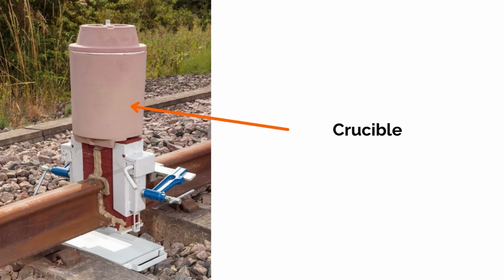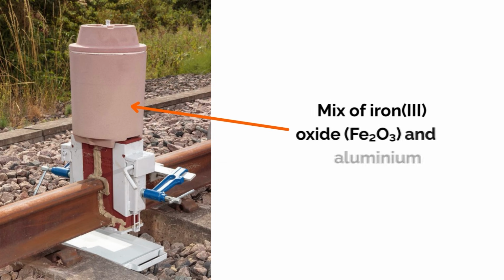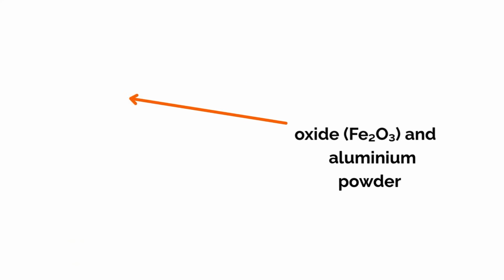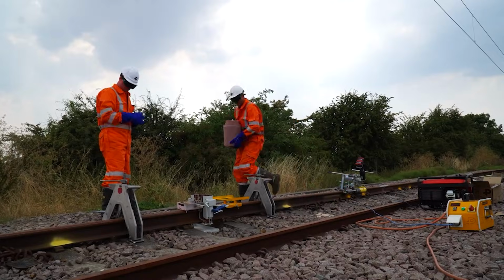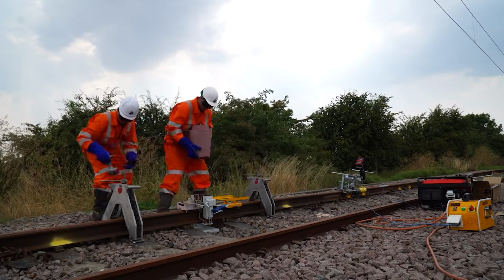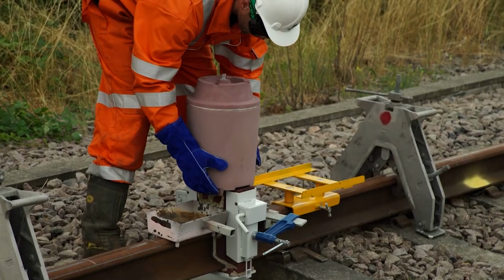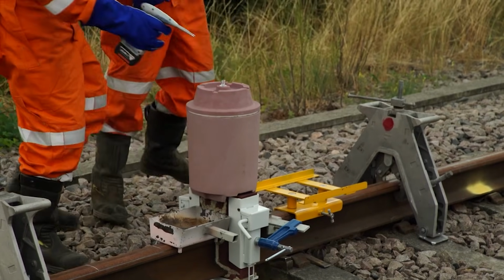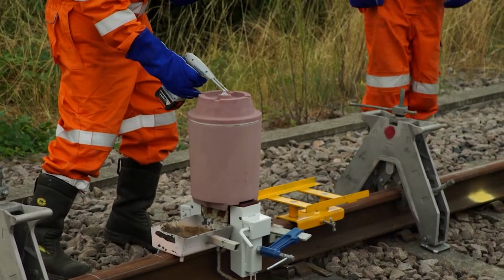This is where the science takes over. Inside the crucible, above the rail, sits a pre-packaged portion, a precisely measured mix of iron oxide and aluminium powder. This pre-packaged mix is known as a portion, a single-use charge engineered with the exact ratios of the materials needed for one weld. It doesn't react on its own, it needs a deliberate trigger.